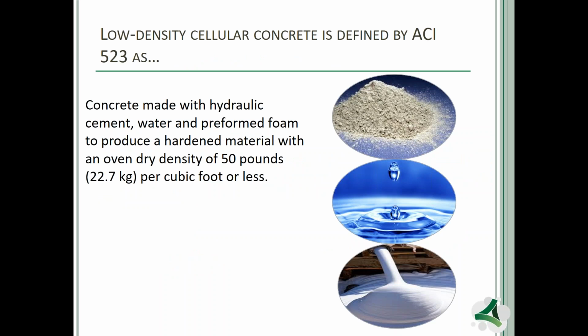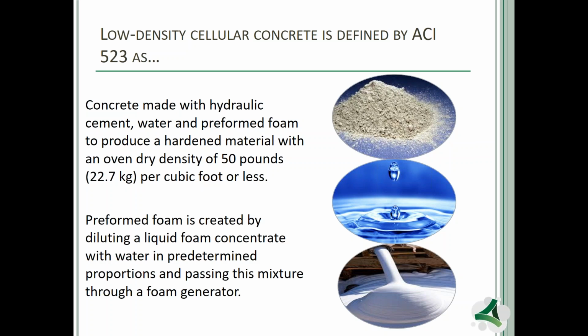I would like to start off by reviewing the definition of cellular concrete under the ACI 523, which is a material that is a mixture of cement, water, and preformed foam, and a key element is that it is under 50 pounds per cubic foot. Erics Industries does not get involved in the installation of the materials, but in the manufacturing of the foam portion. So we do the chemistry of the air bubble. Every gallon of concentrated liquid will produce anywhere between 110 to 220 cubic feet of foam. So it's a tremendous amount of foam all the way.